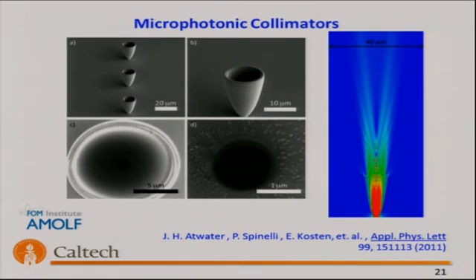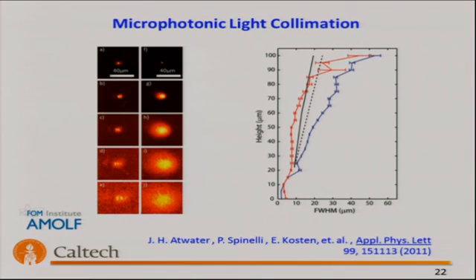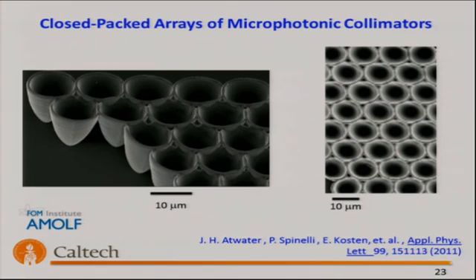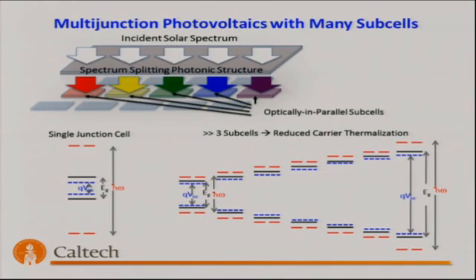And this is a full-wave simulation of light being directed out of such a structure. And this shows the transmission through a bare aperture with no light director, and an aperture with the director, showing the influence of collimation. So we think this is in fact possible. You can actually build whole arrays of these structures and build these as a sort of microphotonic layer on the surface of a solar cell to enjoy this efficiency benefit.